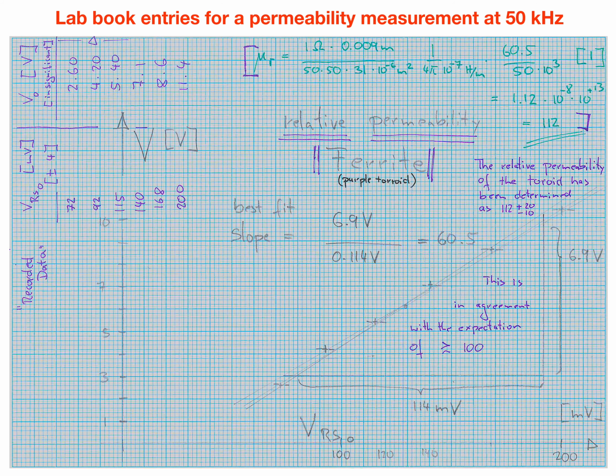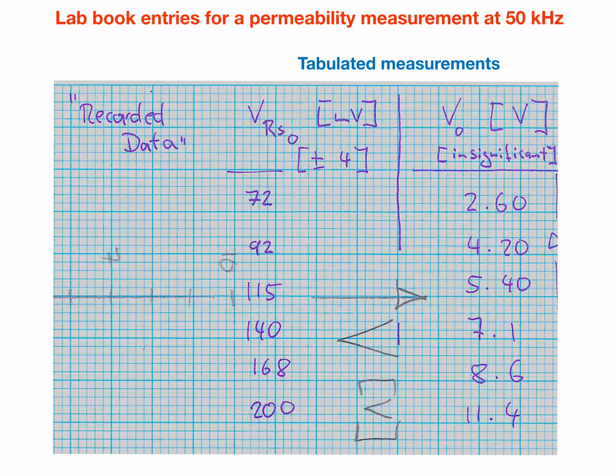This is an excerpt from a lab book record for a measurement like this. At a frequency of 50 kHz, 6 pairs of voltages were recorded and then graphed. Finally, the relative permeability of the toroid was derived. The table shows measurements for VRS in millivolts and with an uncertainty of plus minus 4 millivolts. In contrast, the voltages recorded across the secondary coil, V0, have an uncertainty that is insignificant.